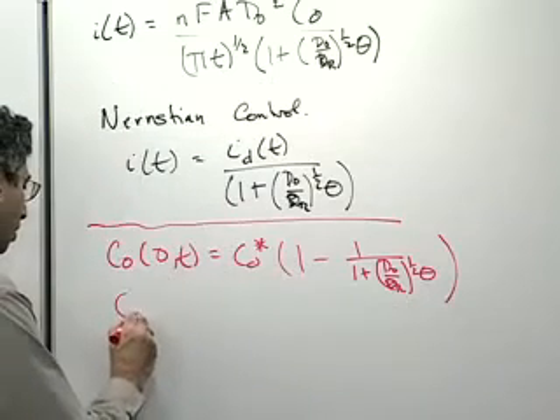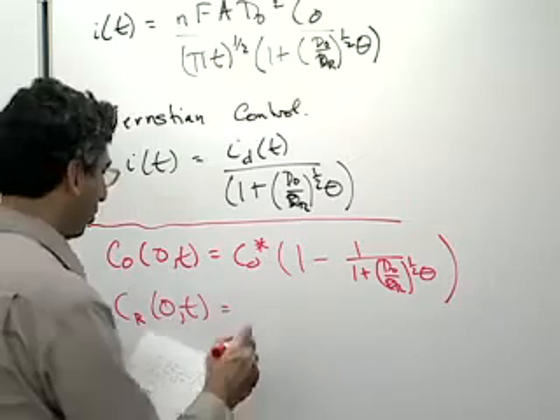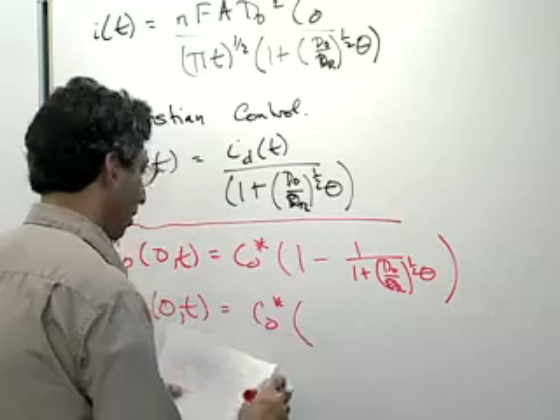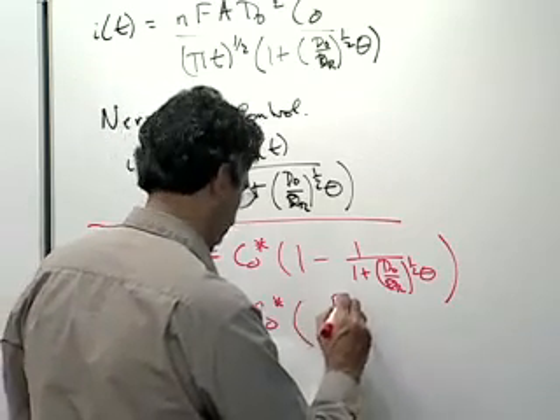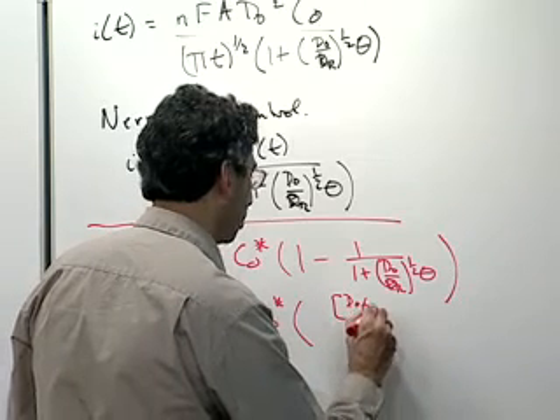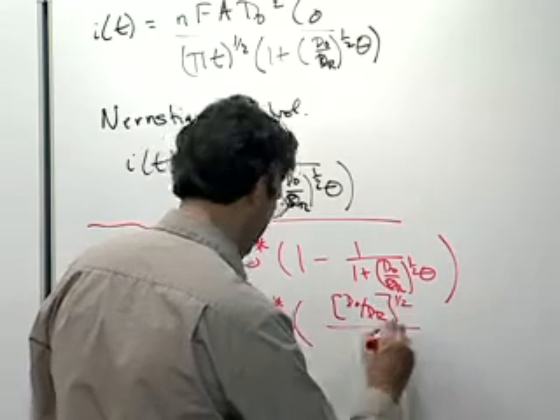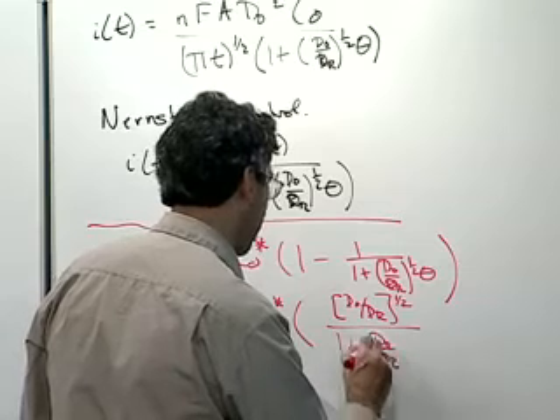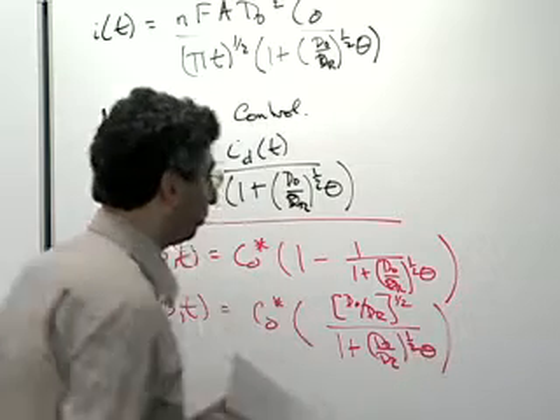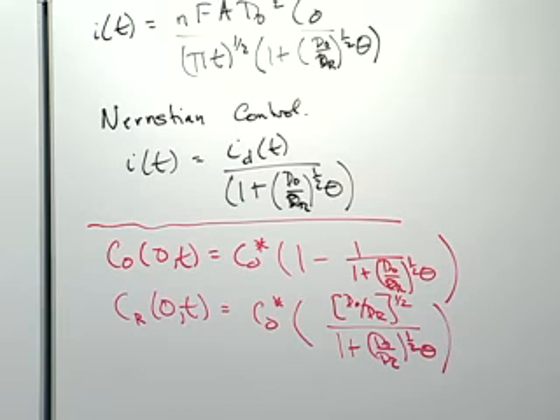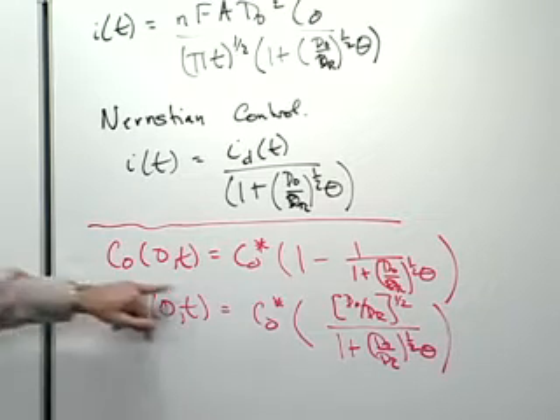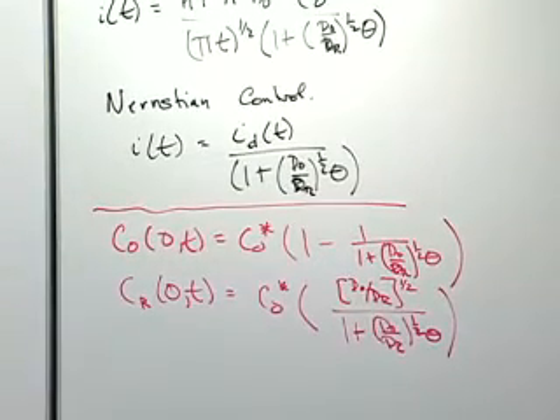And likewise, the reduced species at the electrode is equal to the bulk concentration of the oxidized species times the ratio of diffusion coefficients divided by this 1 plus D_ox over D_red to the 1/2 power theta. So in other words, the gradient you're establishing here is diminished by what the Nernst equation limits you to, as well as the diffusion coefficients. And again, in handling this, even though I've written out everything explicitly here, we are typically assuming that this ratio is a number close to 1. Life gets more complicated if that's not the case.